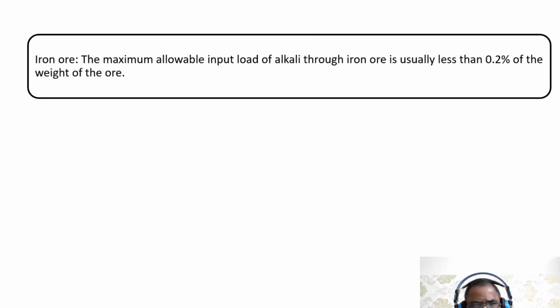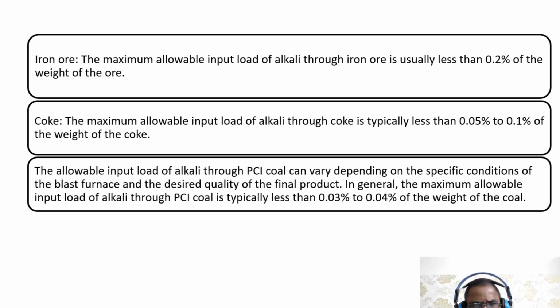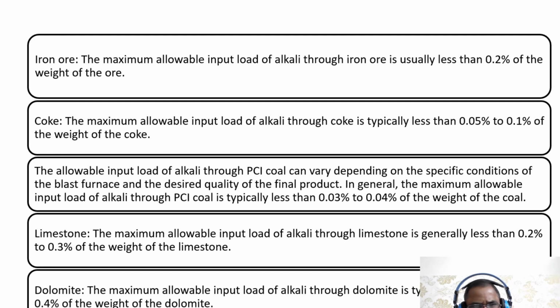Now let's talk about the allowable alkali loads for key materials in the blast furnace. This is also going to be a very important aspect in our daily operation of the furnace. Iron ore less than 0.2% of the ore weight, coke typically less than 0.05% to 0.1% of the coke weight. PCI coal, which is very important, generally less than 0.03% to 0.04% of coal weight. And limestone generally less than 0.2% to 0.3% of the limestone weight, and dolomite simply 0.3%. These strict limits highlight the need for precise alkali management, crucial for maintaining furnace efficiency. As we delve deeper, we will explore how these limits shape the blast furnace dynamics.